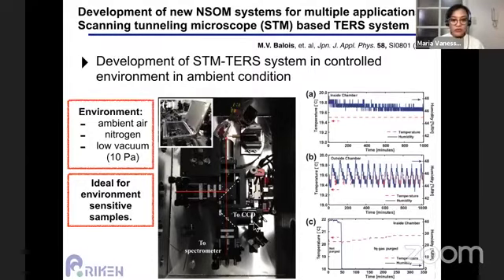This system can also be compatible with nitrogen. If you want to purge nitrogen into the system, the humidity actually goes to zero, which is very nice for samples which are sensitive to the atmosphere, particularly highly oxidizing samples. Now, let me shift from the AFM to the STM.